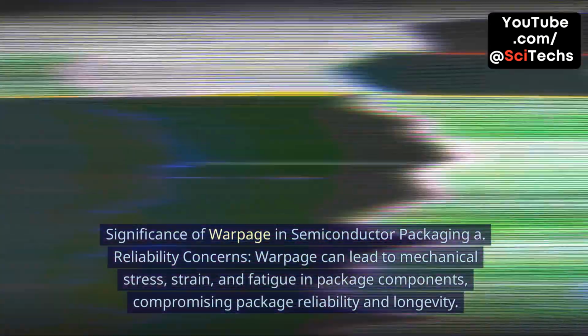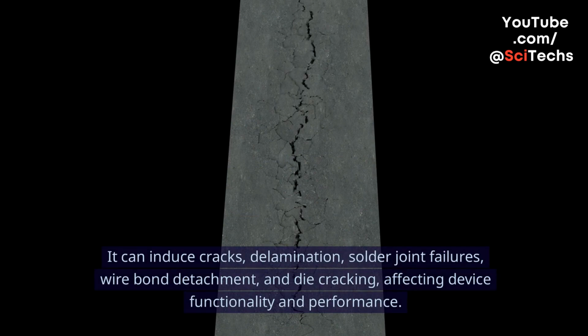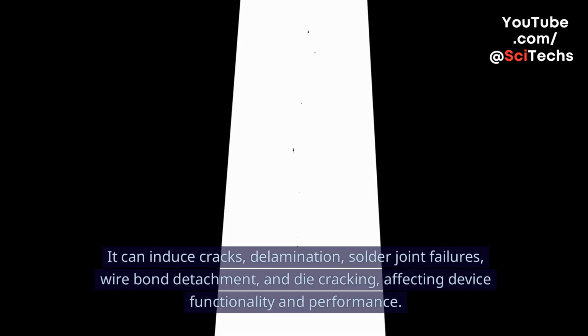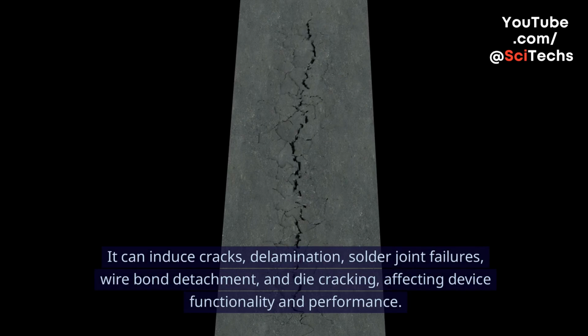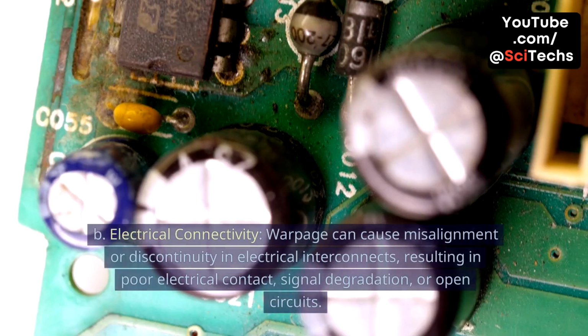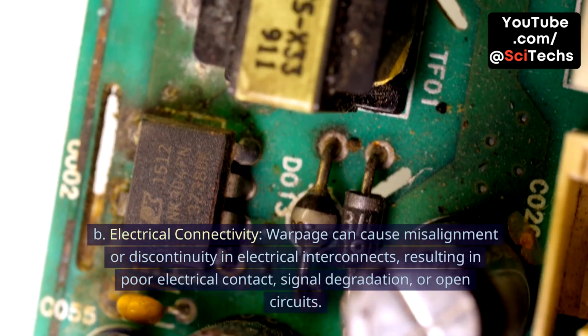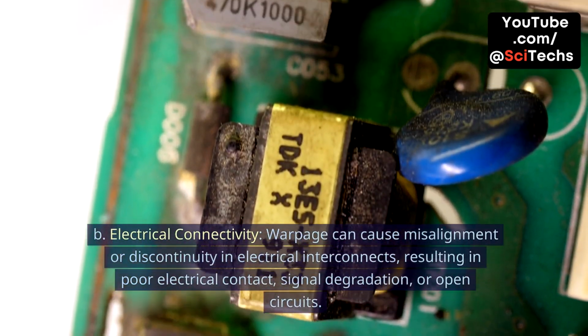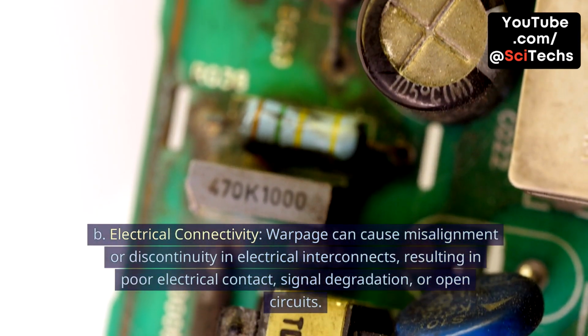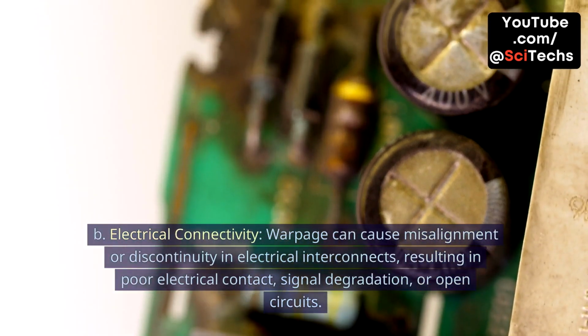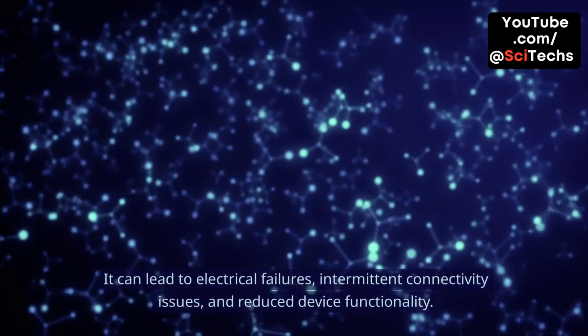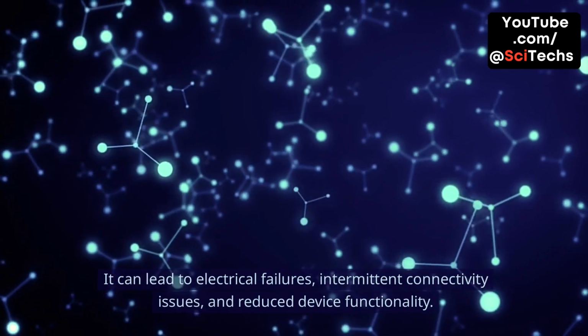2. Significance of warpage in semiconductor packaging. A. Reliability concerns. Warpage can lead to mechanical stress, strain, and fatigue in package components, compromising package reliability and longevity. It can induce cracks, delamination, solder joint failures, wire bond detachment, and die cracking, affecting device functionality and performance. B. Electrical connectivity. Warpage can cause misalignment or discontinuity in electrical interconnects, resulting in poor electrical contact, signal degradation, or open circuits. It can lead to electrical failures, intermittent connectivity issues, and reduced device functionality.